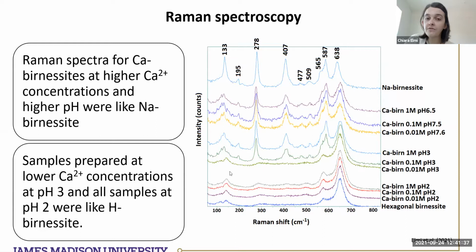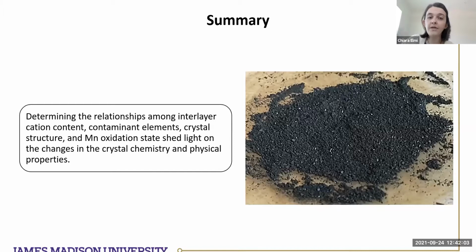The Raman spectroscopy confirmed what we noticed with the X-ray diffraction, and it also showed that the lower calcium concentration at pH 3 and all samples at pH 2 switch to a structure that is more hexagonal. So we determined the relationship between the interlayer cation, possible contaminants in the solution, the crystal structure, and the manganese oxidation state. So we shed light on the mechanism that generates a change in the crystal chemistry and the properties of these objects.